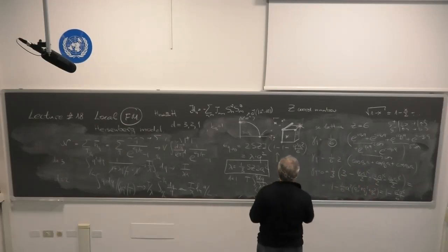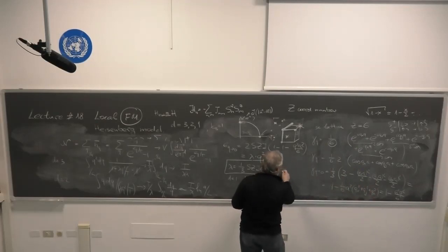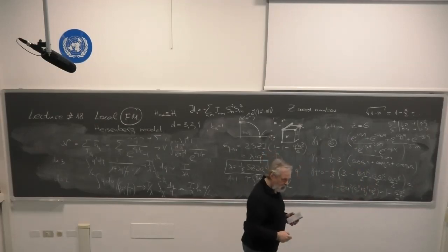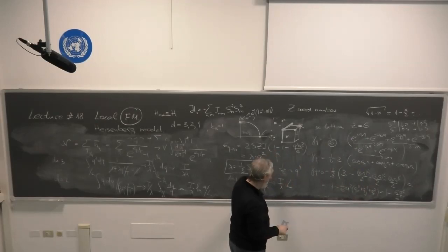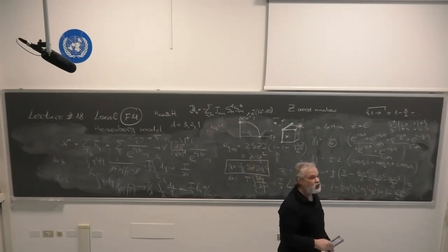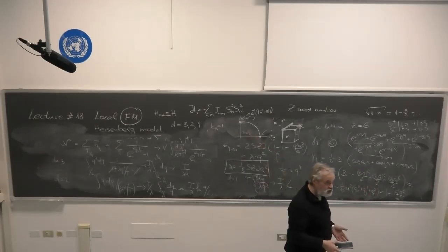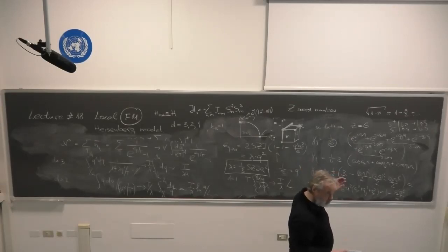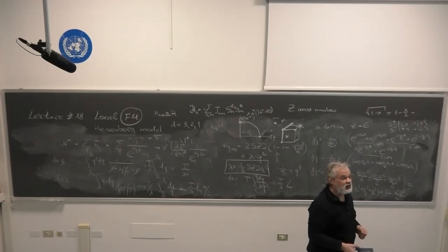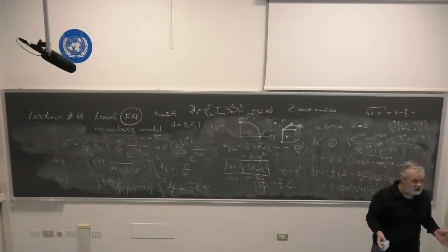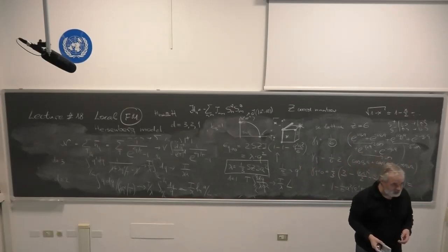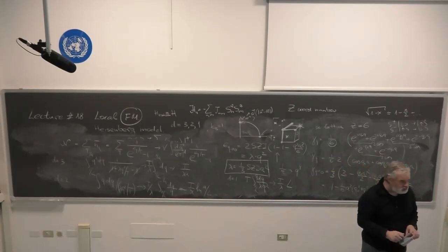It's quite a complicated problem. However, if you do that, you will get that the inverse lifetime at small q is proportional to q to the fourth power. And this is a good sign, because the spectrum is proportional to q squared, and the inverse lifetime is proportional to q to the fourth. So as long as you are in the long wave limit, magnons are well-defined excitations. However, in the vicinity of the critical temperature, magnon-magnon interactions become stronger, and you have less and less well-defined magnons, because temperature also comes into consideration. The full-fledged theory of quantum ferromagnets at arbitrary temperature goes far beyond the topic of my course. If you are interested, you can read it in some books.